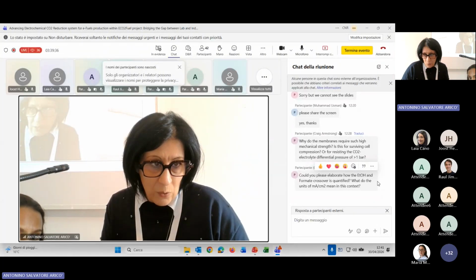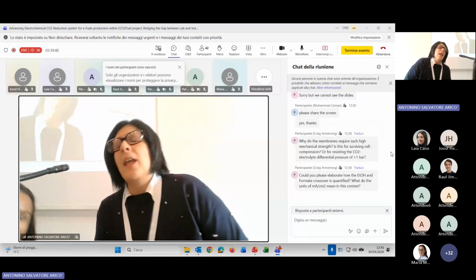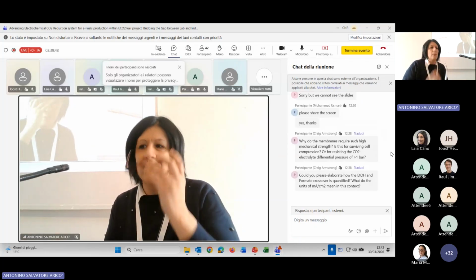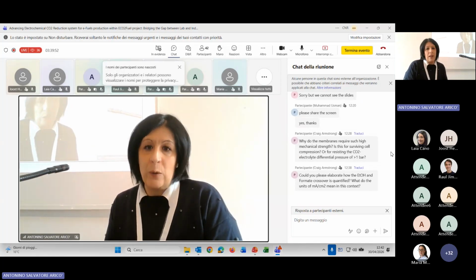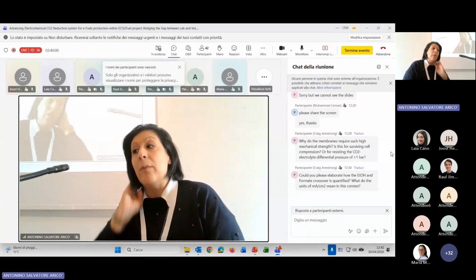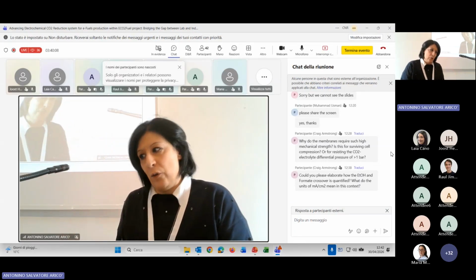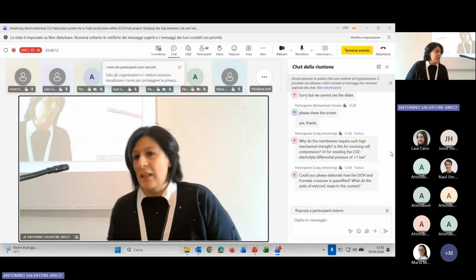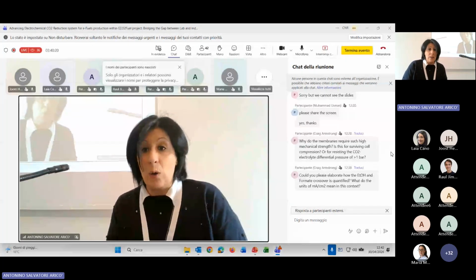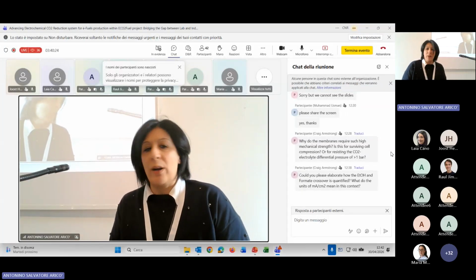during the operation. How is the ethanol and formate crossover quantified? What are the units mainly? Okay. Generally, we have a target of the project in milliampere per square centimeter. So I reported this target, but by the Faraday law, we were also able to calculate the moles of ethanol and formate crossover. In this case, if I remember correctly, the moles are very similar between ethanol and formate. This is due to the different number of electrons involved in the reaction, which is higher for ethanol than for formate. So it is comparable in terms of moles, and different in terms of milliampere, but it is reported in milliampere per square centimeter because it is a target of the project.